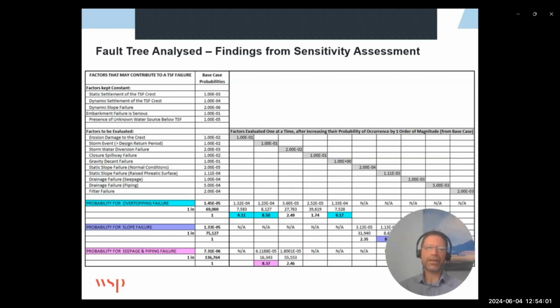if we look at probability of overtopping failure, the factor that played the biggest potential role was erosion damage to the crest. Another factor that might have a big effect, that it's quite sensitive for, is a storm event in excess of the design return period. And the third factor identified for this failure mode was the effect that a potential gravity decant failure could have on the failure mode.